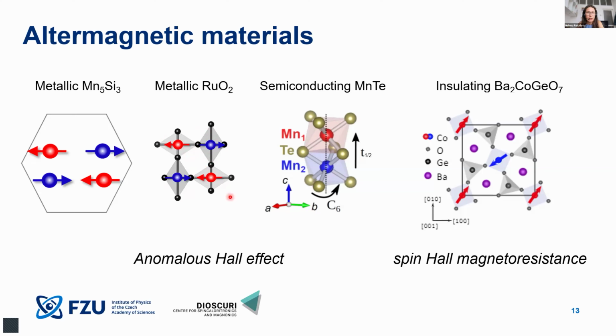However, there are also a little bit more complicated cases, such as, for example, manganese telluride, where again the tellurium cages are rotated with respect to each other, but it's a combined rotation and translation. It's some sort of screw symmetry, but again, this together allows for breaking of the corresponding symmetry. So this is another well-known altermagnet. And also Mn5Si3, which I will also mention during the talk. Here it's not directly the positions of the non-magnetic atoms, but the underlying lattice. So the change of the lattice from, let's say, tetragonal to hexagonal already allows for the breaking of the symmetries, and then this material also allows for the altermagnetic effects.